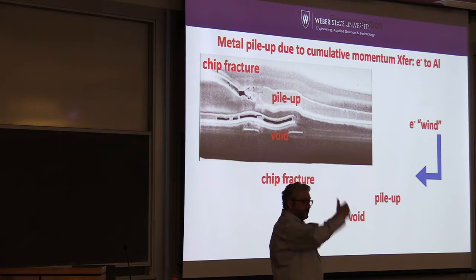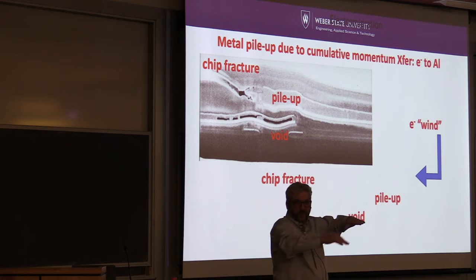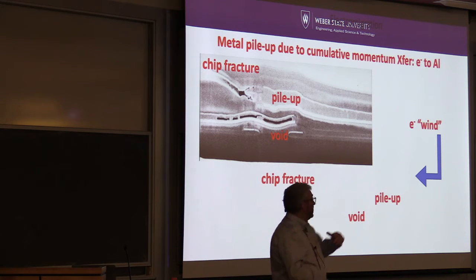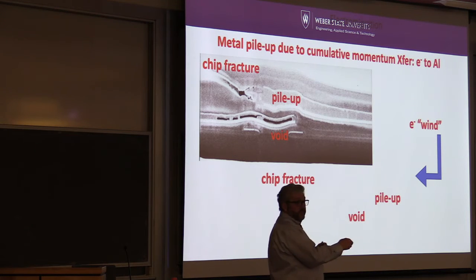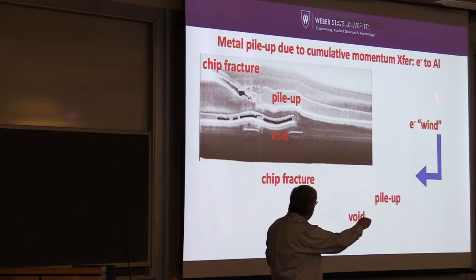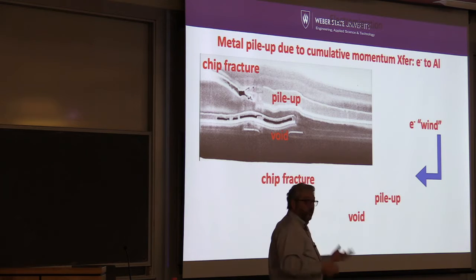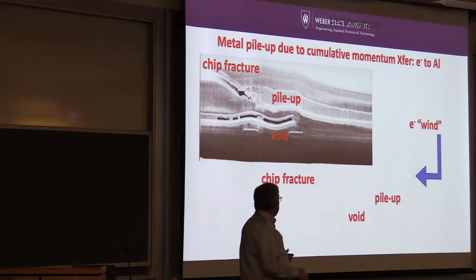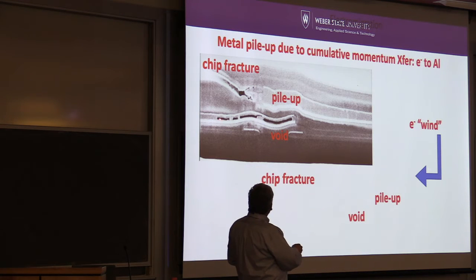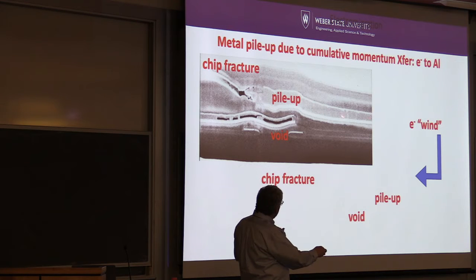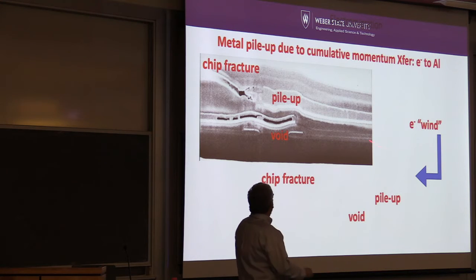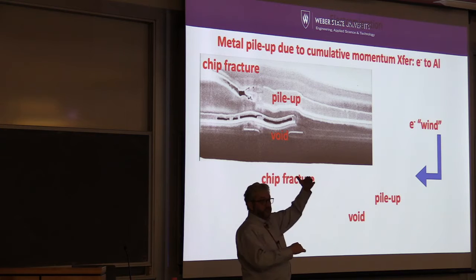So imagine now, here's one of the chips that I looked at years and years ago. This is one of those metal lines. This is a cross-section. Now, the picture I showed just a minute ago was from the top view. Now I've used a focused ion beam to cross-section through a metal line. There's a metal line, there's a metal line, and then there was a vertical interconnect, what we call a via, between those two. And the test structure had been dumping current through this metal line for a long period of time. And so you get the momentum exchange that pushes atoms from one side of the metal line over to the other side. So here's the equivalent. This is the original thickness of the metal line right here. Now you've got voiding, and then all those atoms pile up where they can't go any further. And in this case, they piled up to the point where it actually fractured the surface of the chip.